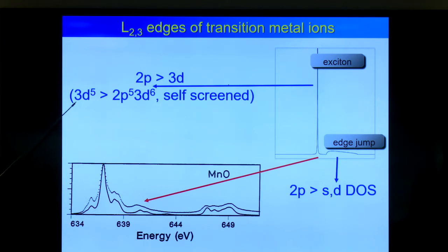So what I do is I say my ground state is d5, and I make a core hole, I put the core hole in 2p, and I put the electron in 3d, and then I calculate this state and that state, and I calculate all the transitions from there to there. But if you approximate your system as d5, you neglect everything. You neglect chemical bonding, and still you can explain your experimental spectrum in great detail. So that was the surprising part, that this actually works.